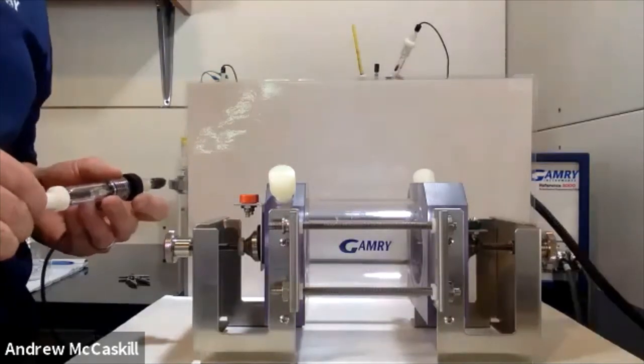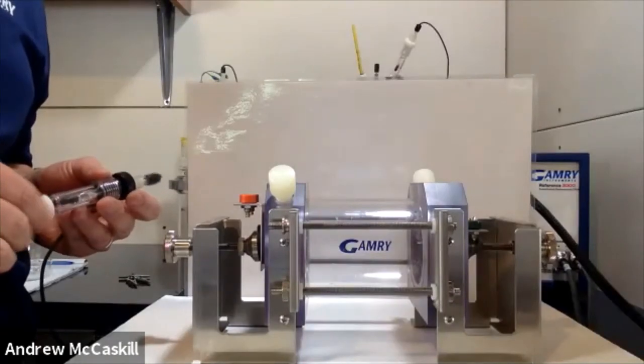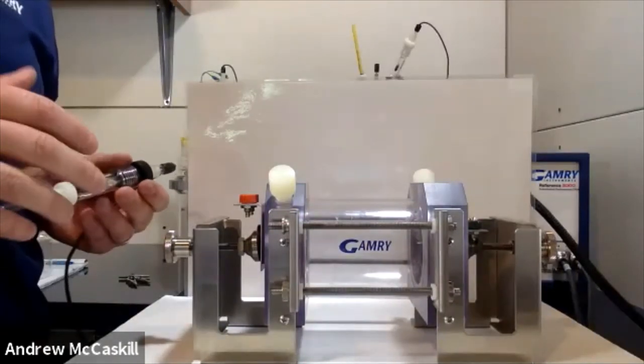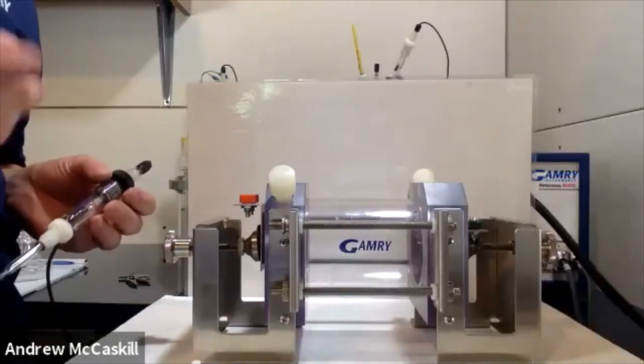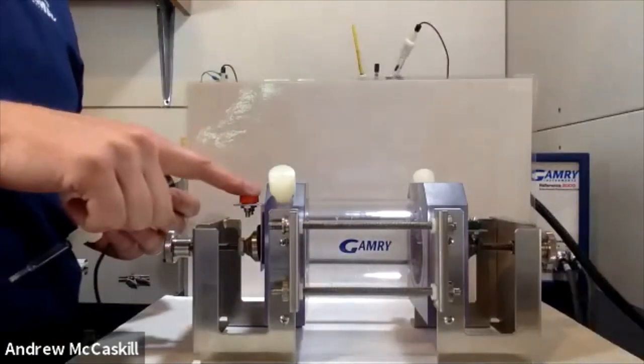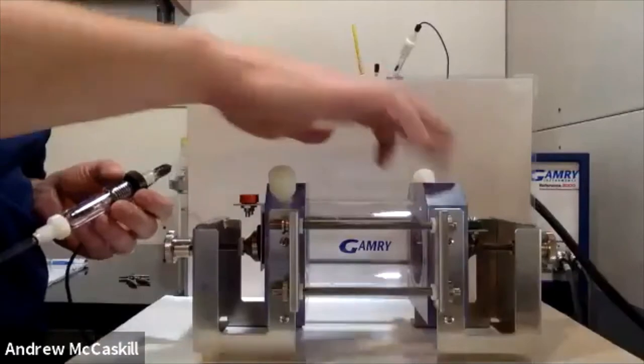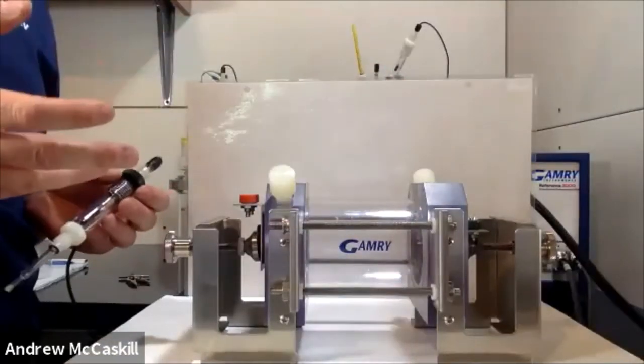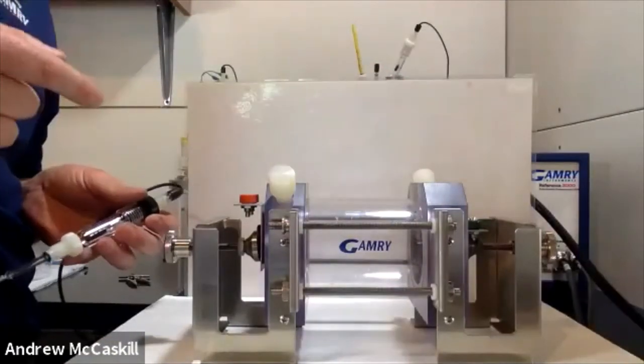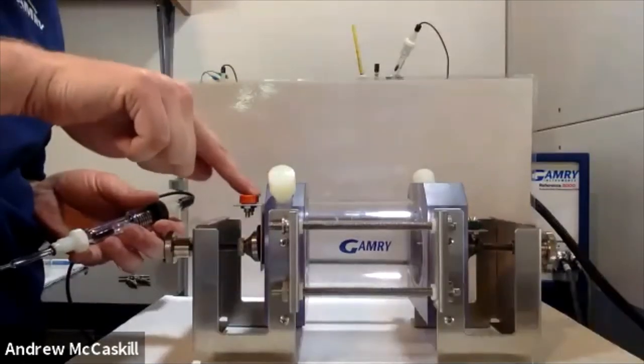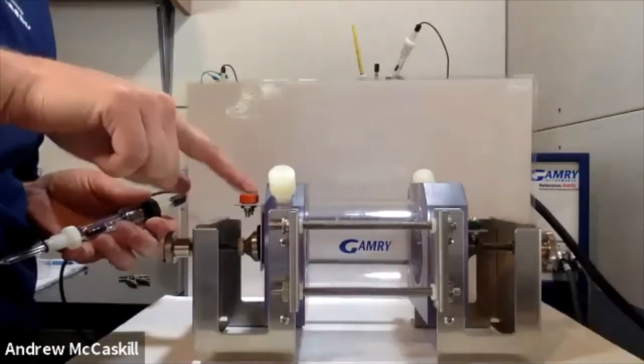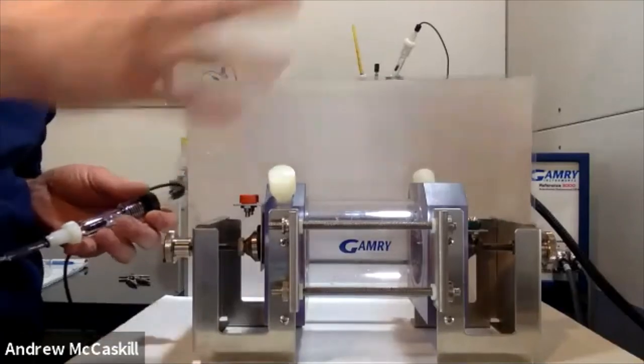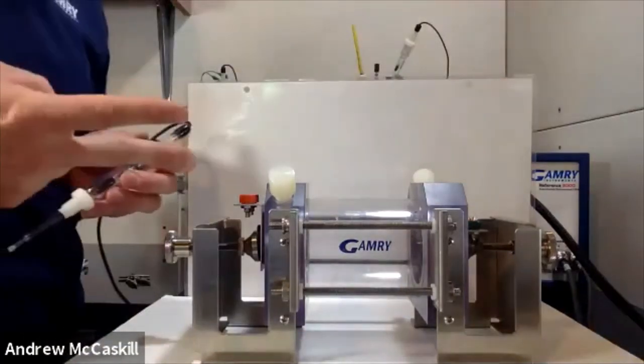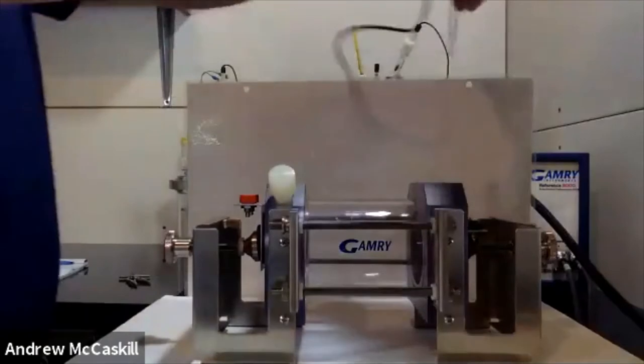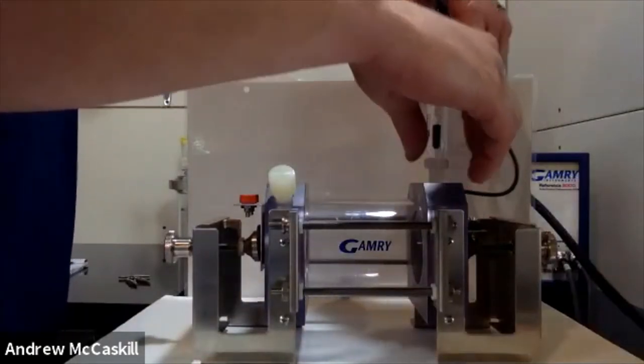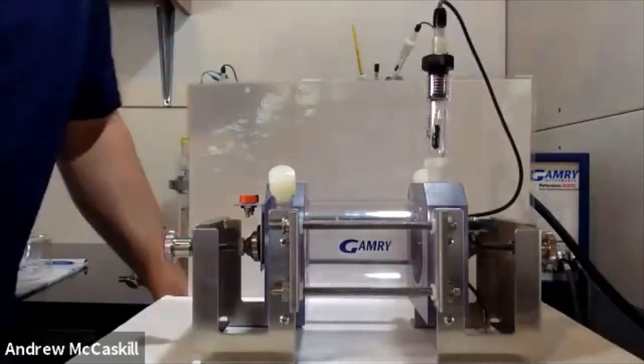Yes. So generally you want to have a larger counter electrode than the working electrode, but the reason for the larger size is you don't want your counter electrode to be limiting the current that could be flowing to the working electrode. So that's the idea of having a larger surface area. I'll also add that with your counter electrode, you want to make sure there aren't any reactions taking place on it that are going to affect your measurements. So those are kind of the two criteria. Depending on the kind of experiment you're running, yes, you might need a larger surface area.